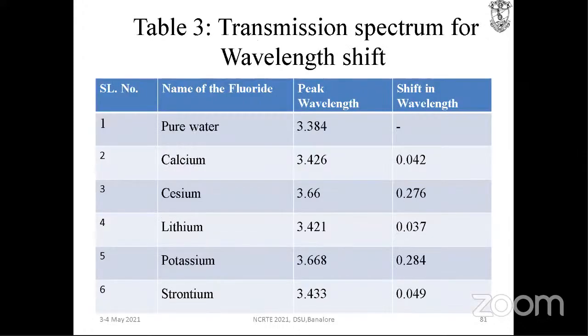For pure water, the wavelength is 3.384. That is the signature of the pure water wavelength. If it is contaminated with calcium fluoride, the wavelength is 3.426 and the shift in the wavelength is 0.042. Once again, for calcium fluoride, the signature is 3.426. For cesium fluoride, it is 3.66 and the shift in the wavelength is 0.276. So depending upon the shift in the wavelength, we can tell which type of fluoride content is there in the water. Okay. Next.